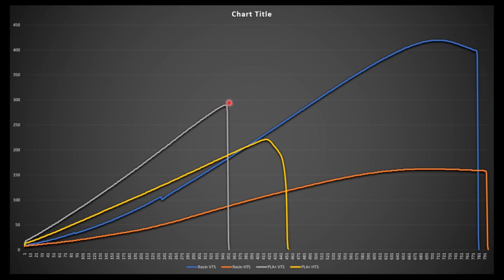It just stretched right to the moment it snapped like a piece of glass, a glass rod, bang, it broke, and right there it dropped right off. So it was pretty brittle in the vertical axis. The PLA Plus horizontally, you can see it yielded, and then it just kind of slowly dropped off and then kind of broke very gradually. It was not a sudden break, and it was a nice controlled, easy break. This is ductile. This is a good way of breaking. The part did not fail suddenly and spontaneously.